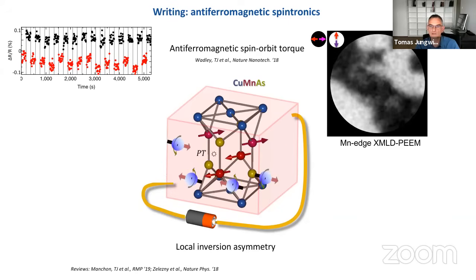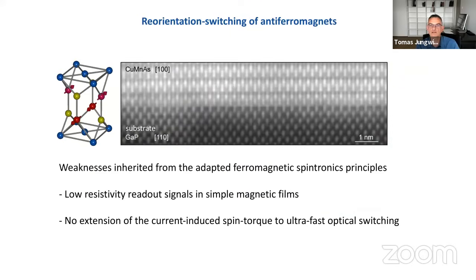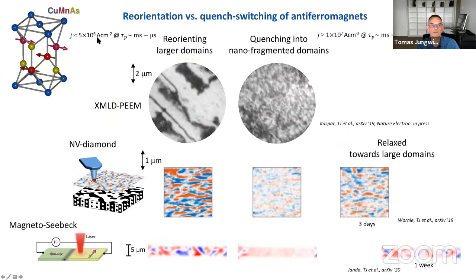Now, when I use the same material, same film, but instead of weaker pulses I apply slightly larger pulses, and sometimes it's very difficult to find the regime where you have this crossover because it's very close by, then instead of reorienting your large domains you shatter them into a nano-fragmented domain state. In response, you see a large increase of the resistivity of your film, which is 2 to 3 orders of magnitude larger than what you see in the reorientation switching.